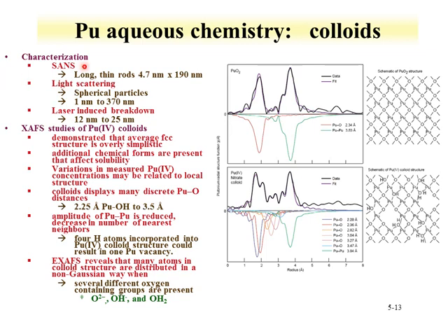Characterization of colloids can be done with a number of different techniques: small angle neutron scattering, light scattering, laser-induced breakdown spectroscopy. Each of these tends to produce different results as far as the characterization of plutonium colloid particle sizes. That has to do with two things. One, the methods themselves. For instance, light scattering is predicated upon spherical particles. And two, the solutions are different. The time between when the solution was made and when the measurement was made will vary. Therefore, the results can vary.